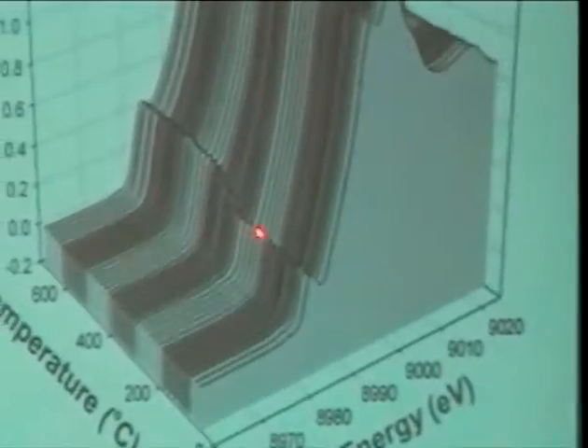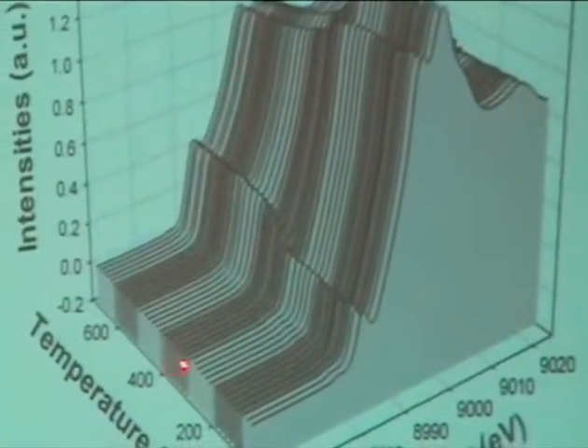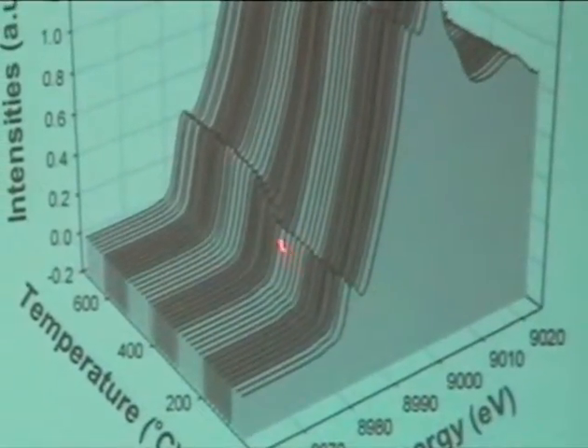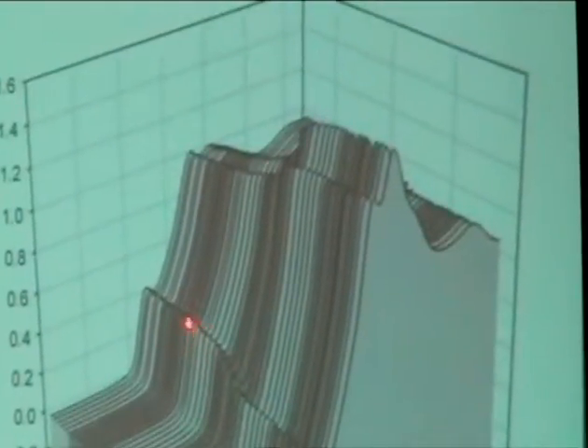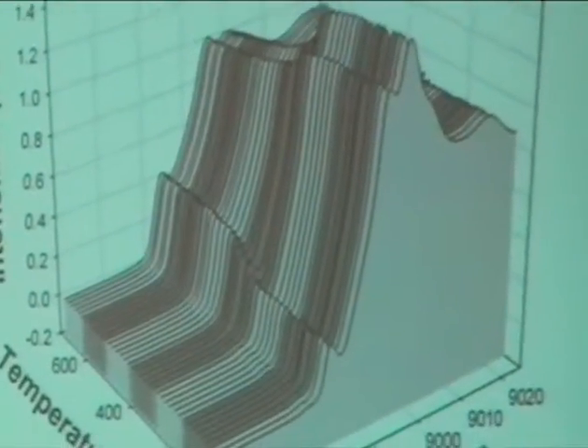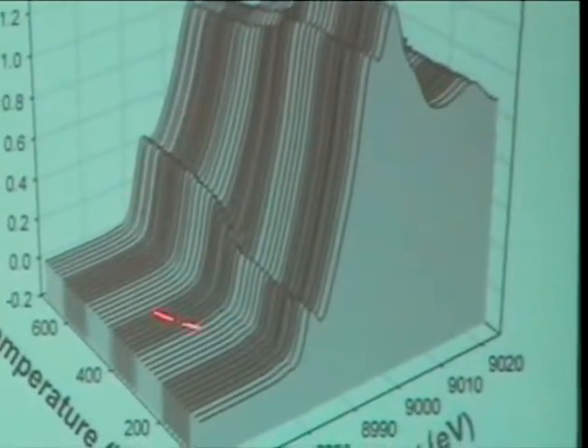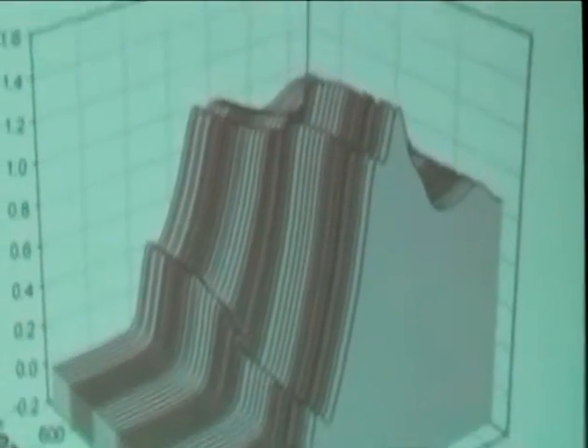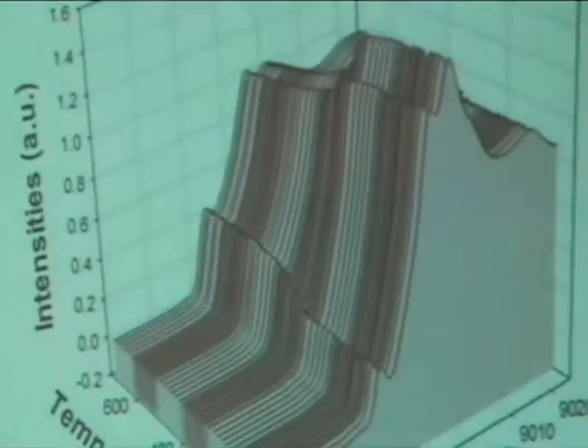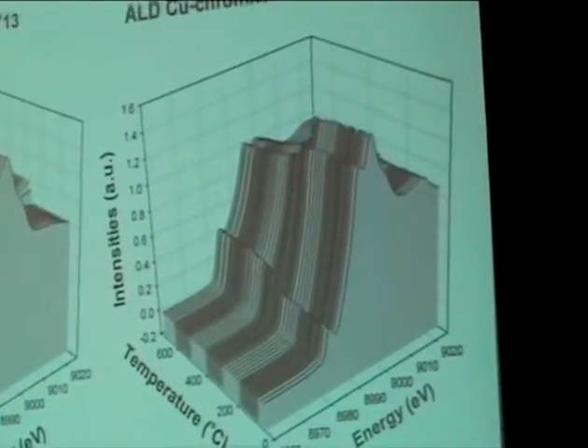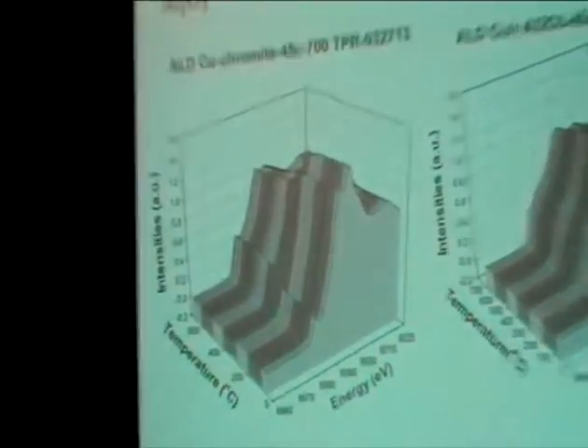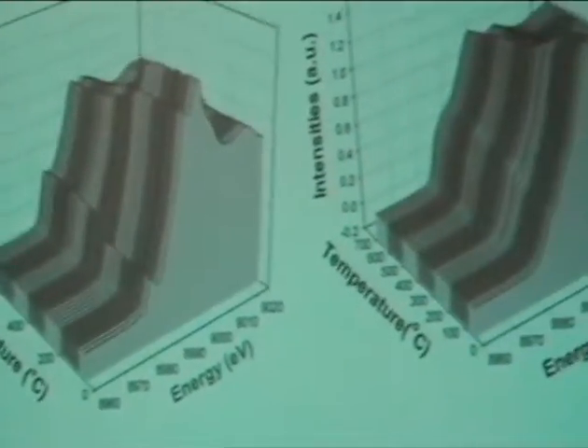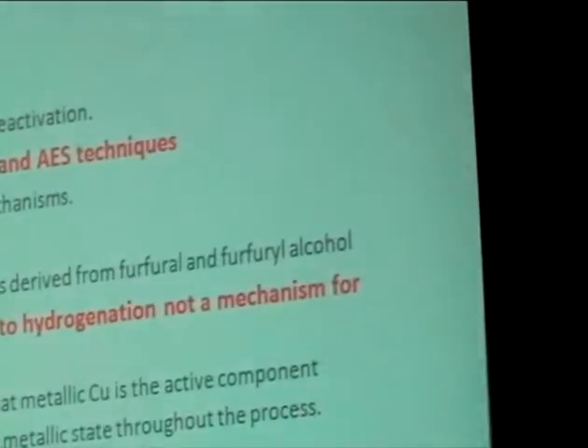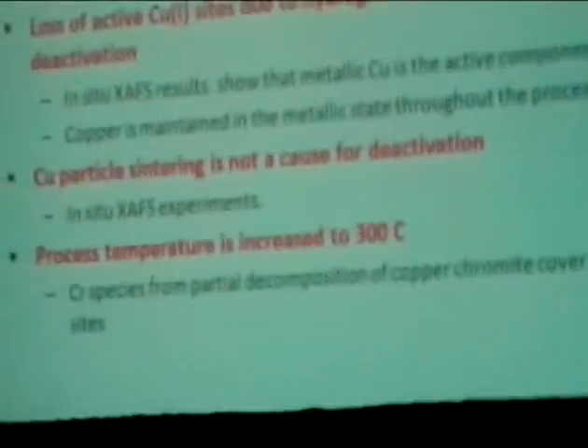But the rest of the material, which is still available for reactions, starts reducing at a much higher temperature, about 300 degrees. And you can see that there's a slow progression to the fully reduced material, indicating to us that there are diffusional limitations in this catalyst, and it's hard to get the hydrogen down to the surface of this catalyst, and that's something we're going to be looking at in the future. In the interest of time, I won't talk about the other material, which is Jim Domesic's material, and go on to the conclusions of this talk.